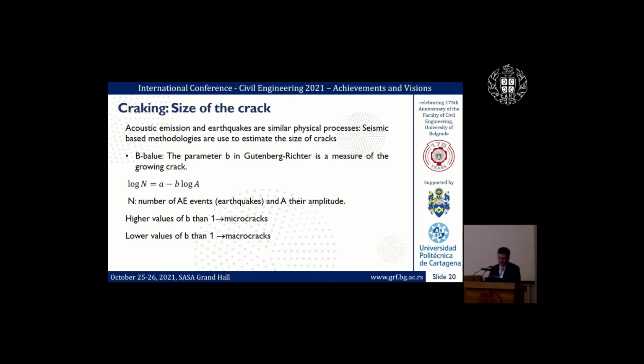If its value is higher, it means that we have many events of low amplitude, so we have what are called micro cracks. And if we have a lower value of parameter b, it means that we have a lot of high amplitude values, so it can indicate that we have a macro crack.